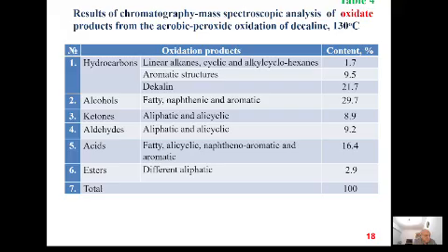The conclusion is that despite hydrogen peroxide being a hydroxylating agent, the influence of air oxygen as co-oxidizer allows bringing the reaction to the stage of acid formation. Total conversion of initial decalin is about 78 to 80%, and the content of acid reaches 16 to 20 weight percent.